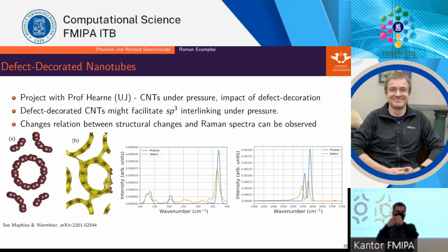So if you have a fiber of carbon nanotubes, unless you twist it really hard, the nanotubes can easily go past each other. So the weak point of a carbon nanotube material is supposedly the weak interaction between the tubes, not the strength of a single tube. But if we can maybe introduce some interlinking, some chemical bonds between different nanotubes, then maybe we can solve the problem. So we do this experimentally.